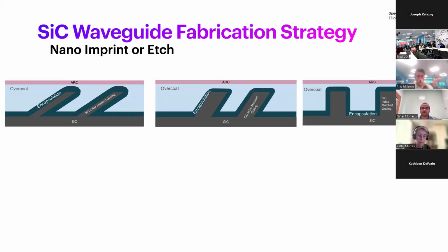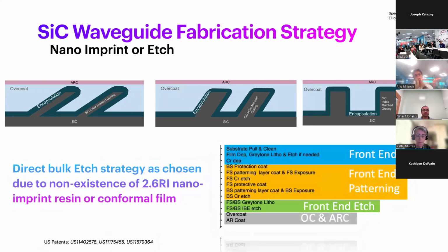Typical fabrication strategies for SRG waveguides that are common in the industry is either through nanoimprint or through traditional semiconductor-style etched paths. Both paths have their advantages and disadvantages that have been extensively covered in various conferences and review papers. Due to the very high index requirement for our gratings and the need for a variety of slant angles, including the steep 60-degree slant, we chose the etch strategy. Unlike glass or lithium niobate, where you need a functional film to etch into to create gratings, as the bulk substrate cannot be etched, in case of silicon carbide, the bulk etch is the preferred path, enabling natively index-matched gratings